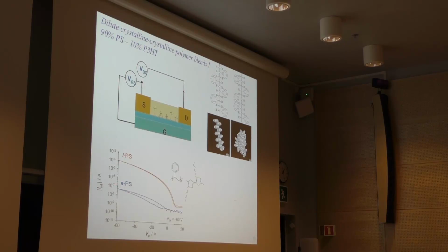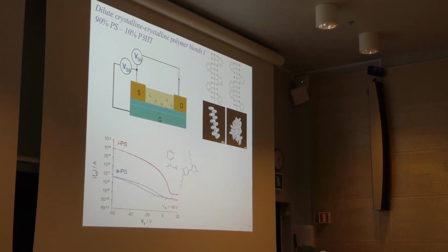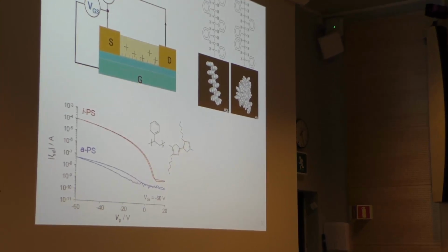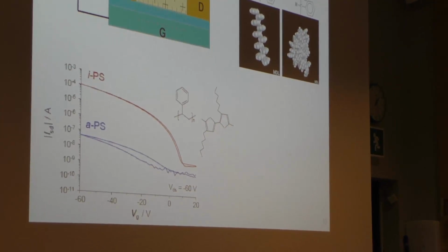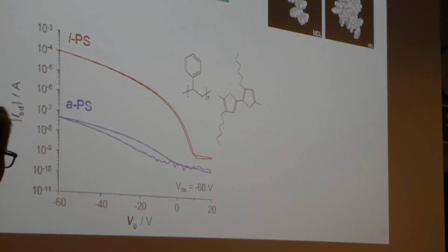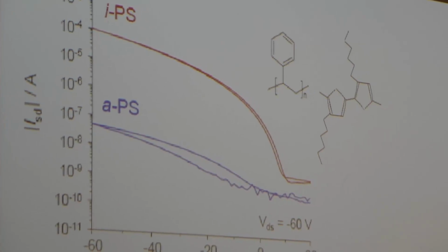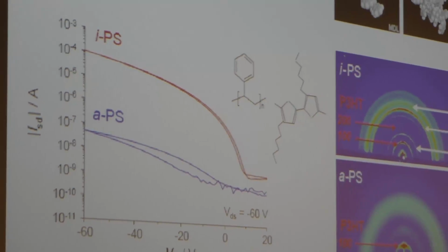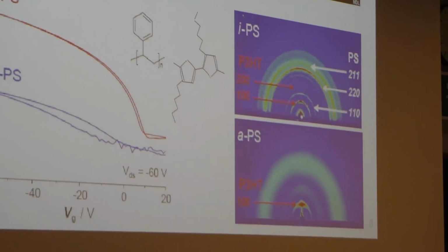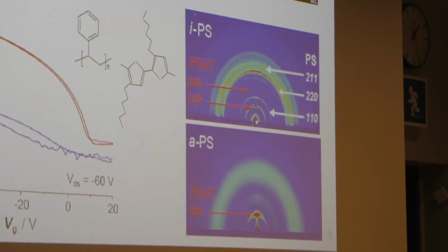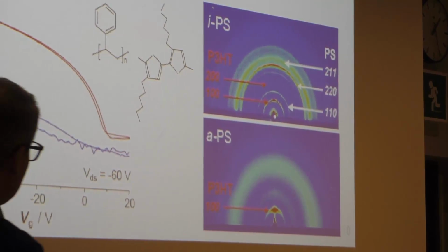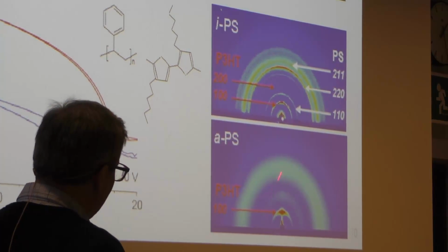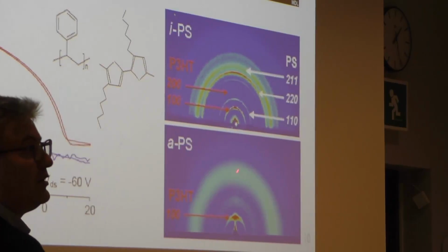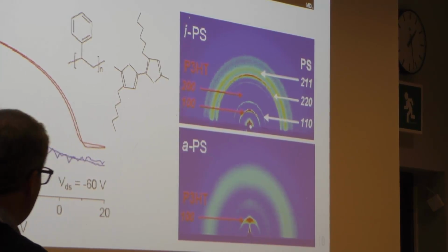polystyrene, which came as a big surprise to us, because don't forget that the polystyrene is electrically sort of dead, right? So you cannot point directly to the polystyrene to find out what the reason is for this change in the source drain current. But if we look at this with the technique that I just described for you, looking at this with the grazing incidence, you can see that the scattering patterns that we obtain are qualitatively different, right?